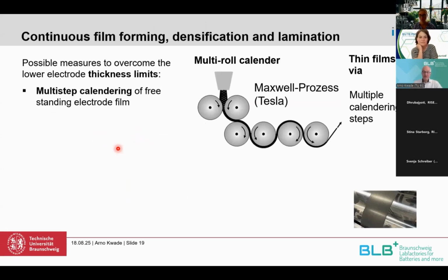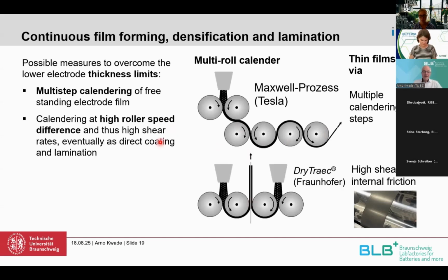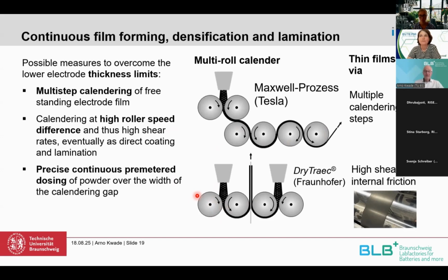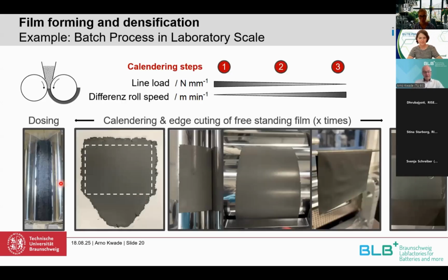One possibility is to have a multi-step calendering, which is a typical Maxwell process. Then we can have high differential speeds between the rollers, also affecting the film thickness a lot, so that you have the right film thickness already with one throughput through the roller gap. And you might be able to have an exact pre-metering into the gaps, and that might also give you a good film thickness.